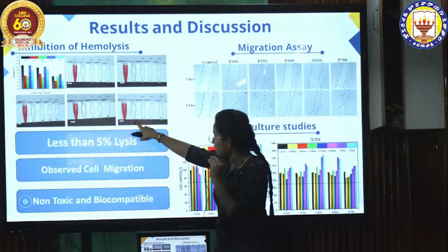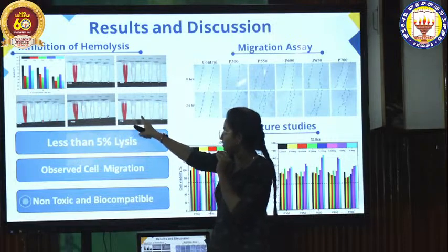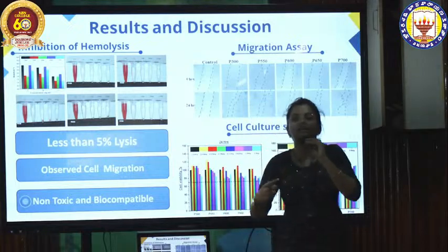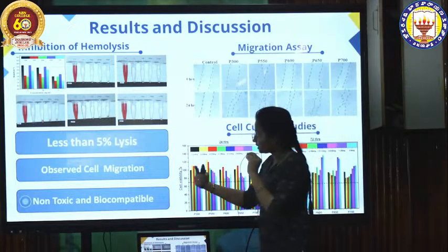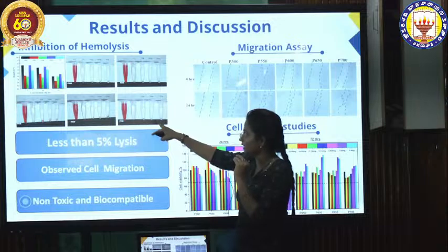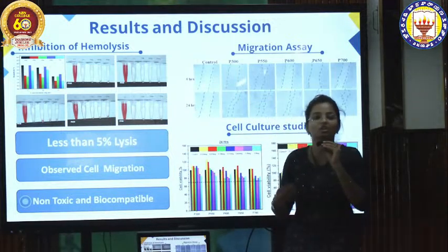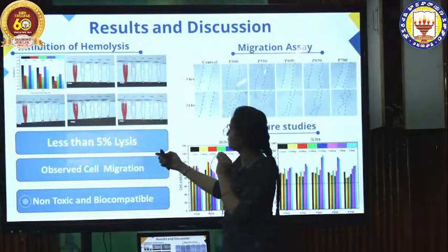When the blood and PBS solution are added to our 5 mg sample, we add 1 ml of blood as well as PBS solution, keep them at rest, and then centrifuge them. After centrifugation, if the blood sample forms a layer on top of our powder, it says that our powder is non-toxic in nature. That means its lysis percentage is low, which has been identified.